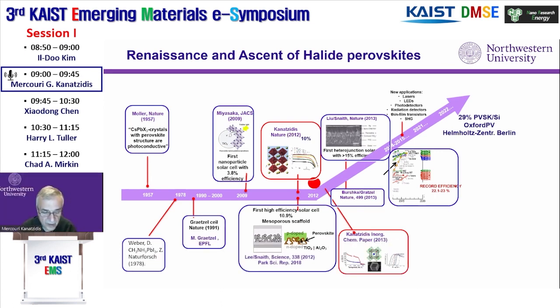The one limitation is that if you have a pure device based on 2D only and not 3D, you can have very high efficiency, but it's never going to be as high as 3D. So that's because, you know, one dimension is still not quite functioning as well as the other two. But when you have this combination, then you solve the performance problem. Another challenge, but again, progress is being made, is to cast 2D films of a particular N value, particular thickness, without getting a mixture of other thicknesses as well.